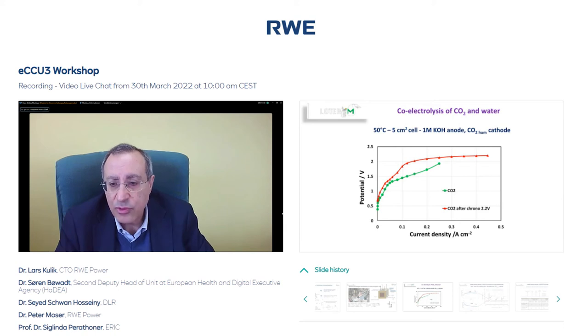If we can move to slide number 16, in the presence of carbon dioxide and cuprite electrocatalyst at the cathode, we can see that, of course, there is a significant decrease of current density. We have something like 300 milliamperes per square centimeter at 2 volts at the beginning of a test, but after prolonged operation, this decreases a little bit. And you can also see a change in the profile because the hydrogen evolution reaction is becoming more important while the electrode is flooded.